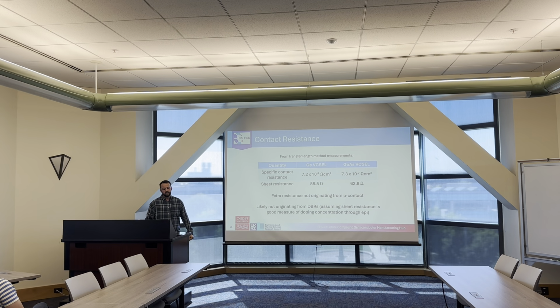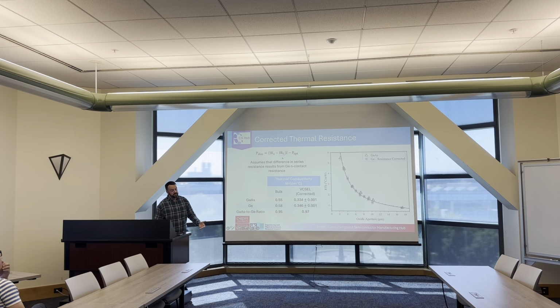So we looked at the contact resistance from the P contact from TLM measurements, both 7 times 10 to the minus 7 ohm centimeter squared. Sheet resistance, comparable as well. So the extra resistance is not coming from the P contact, and is likely not coming from the DBRs as well. So then, if that dissipated power is coming from the N contact, it needs to be corrected from the original dissipated power from the thermal resistances. So we included this RC term here. That's 20 ohms, that's the offset between the measured resistances. And then clearly the plots are a lot closer than they were previously. And then that GaAs to germanium ratio is now 0.97 as opposed to 0.95. So actually a lot closer to the bulk value.